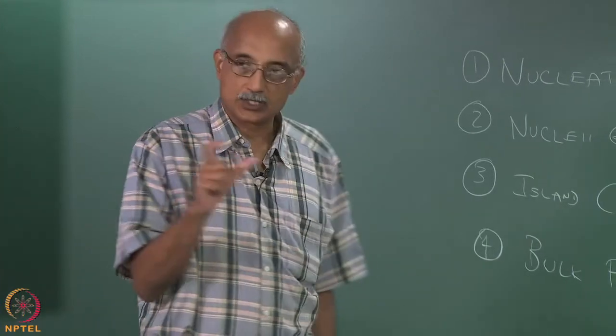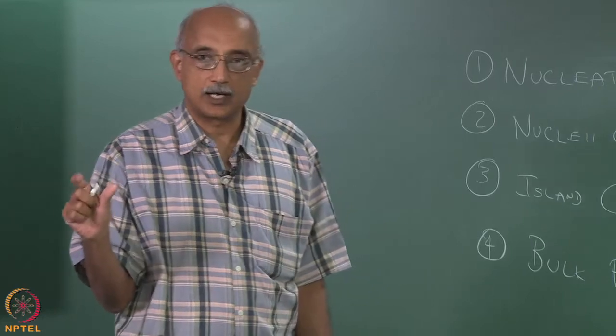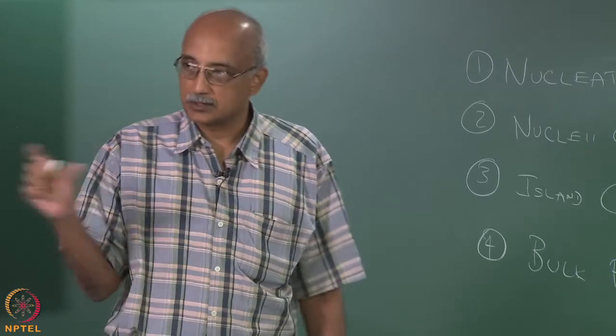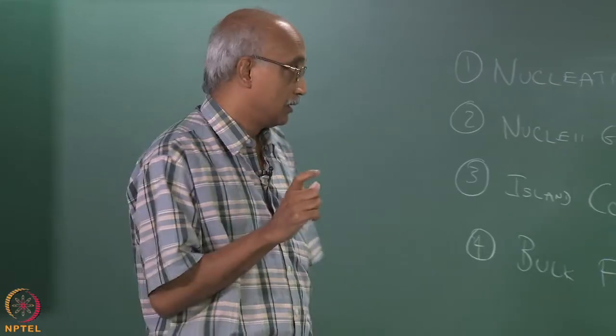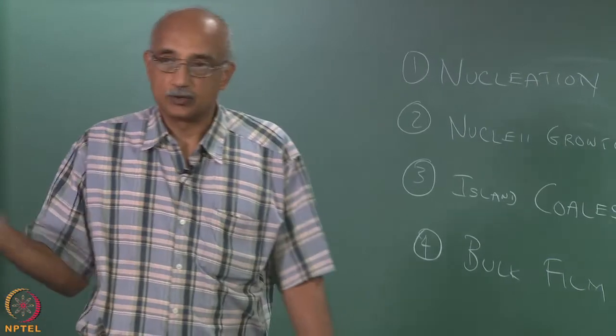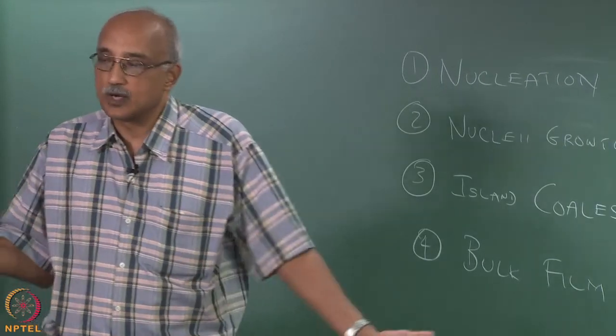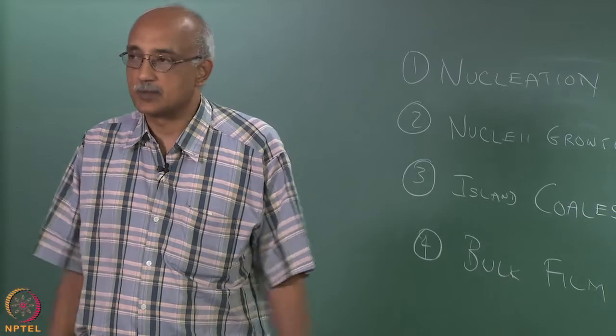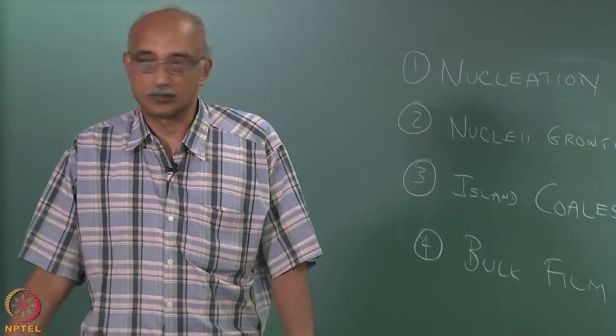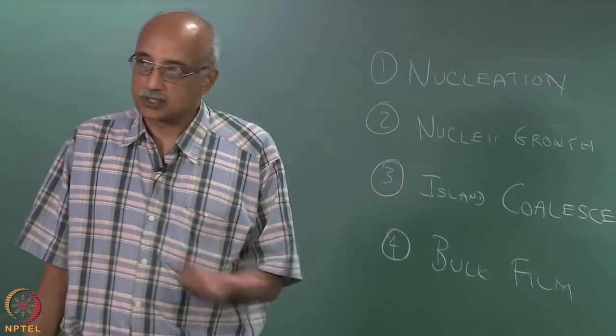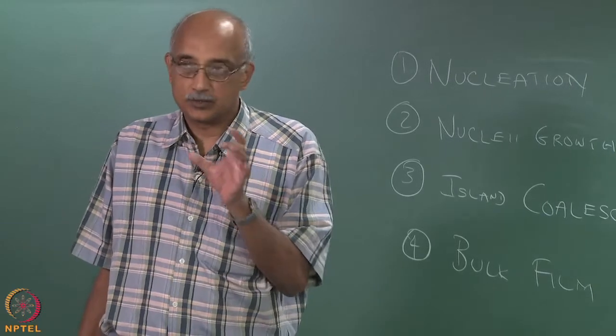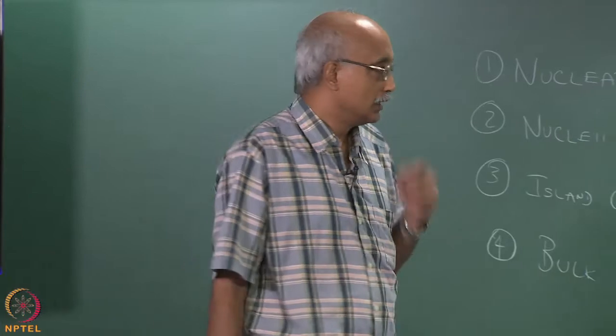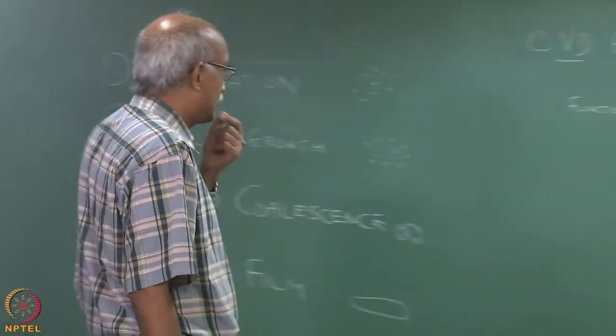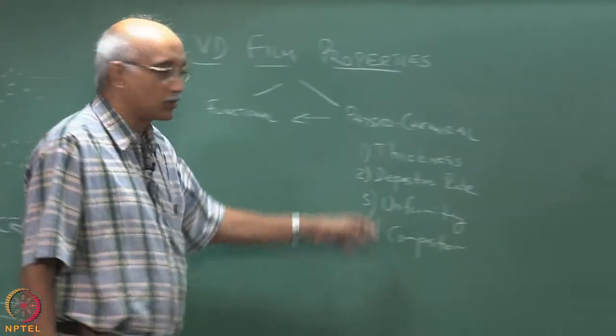set some specifications. What is the thickness range that you want to have? What is the rate at which you want the film to be forming? What is your specification on the uniformity? Do you need plus or minus 1 nanometer variation, or do you need plus or minus 1 micrometer variation over the surface? And the composition, what exactly should be the chemical state of the film that you're depositing on the surface?